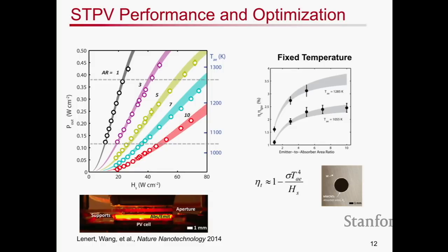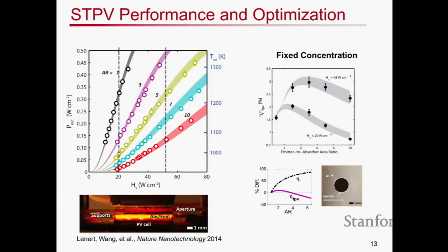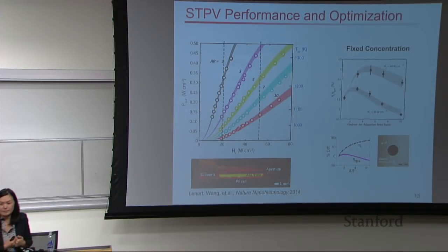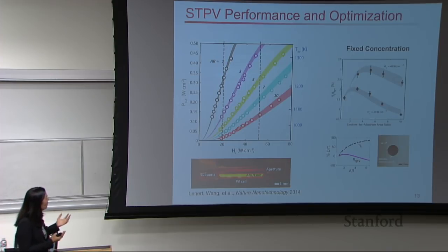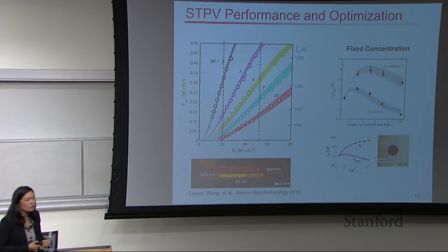Okay? And so if you looked at a fixed concentration, what you start to see is that as you increase the area ratio, your TPV conversion process will decrease. And that's expected because at some point you're going to be operating at a lower temperature such that it becomes not ideal for the PV cell, right? And so there are these trade-offs, and there certainly is an optimal point for a fixed concentration of this overall efficiency as you increase your emitter to absorber area ratio.